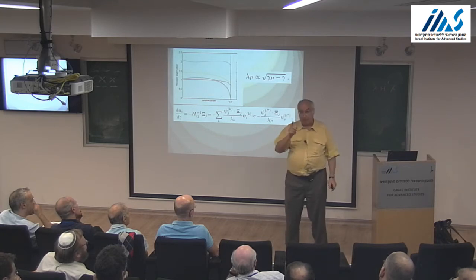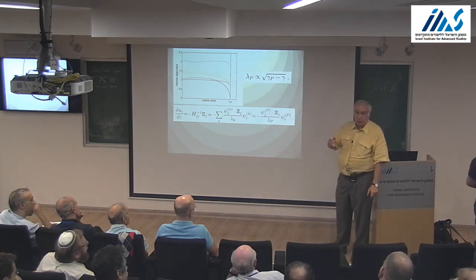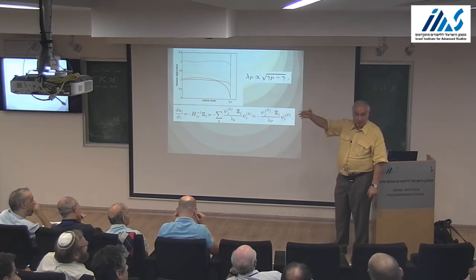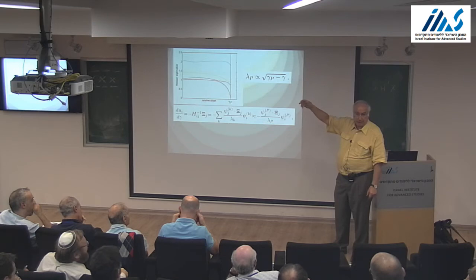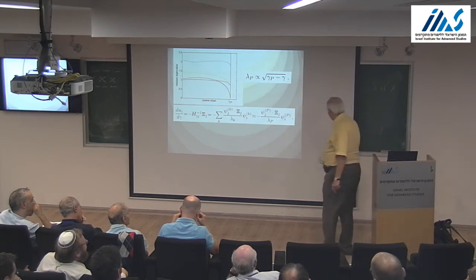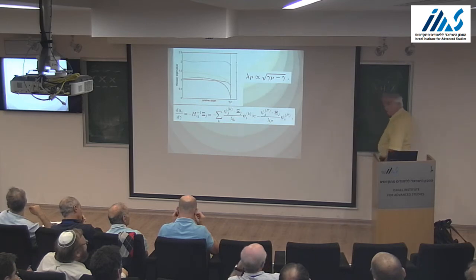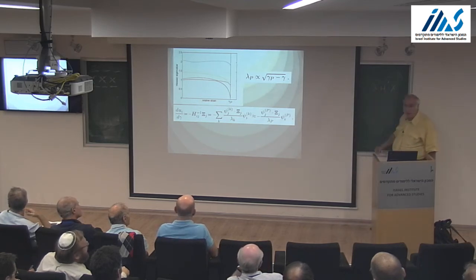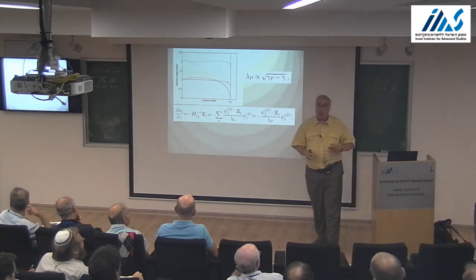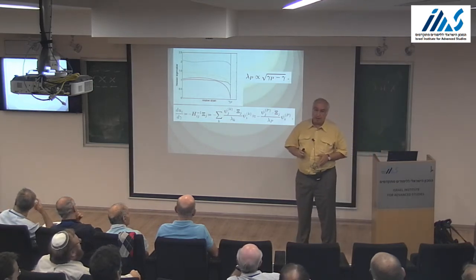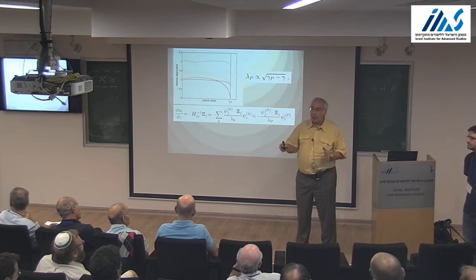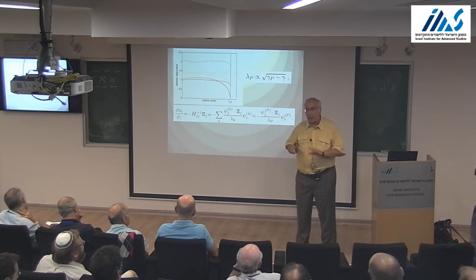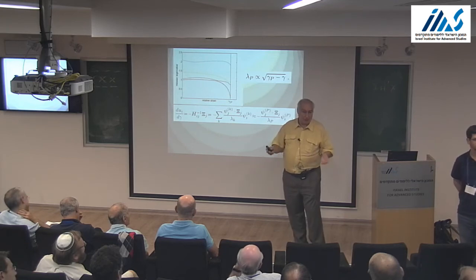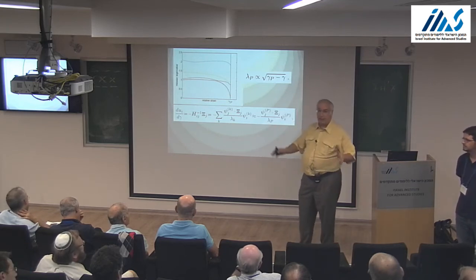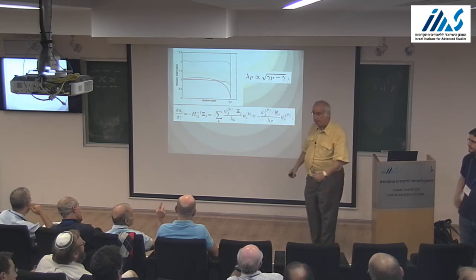So nonlinear theory is in big trouble. If you open Landau and Lifshitz, you would expect that the stress can be expanded in mu times gamma plus something times gamma squared plus something times gamma cubed. Those somethings are now not proportional to H^-1, but H^-3, H^-5, and these go berserk. So the density of states no longer protects them, and we showed already in 2011 that nonlinear elasticity does not exist in this. And this is connected to many interesting things that people are thinking about, like the Gardner transition, where you expect indeed to lose nonlinear elasticity, but this is a different subject, this is a different lecture, but very interesting. Yeah.